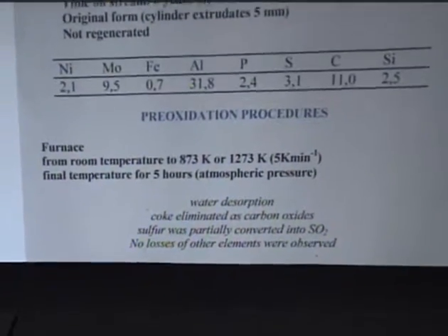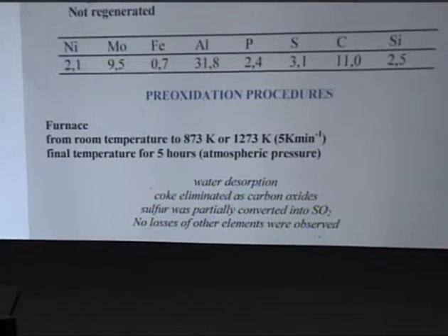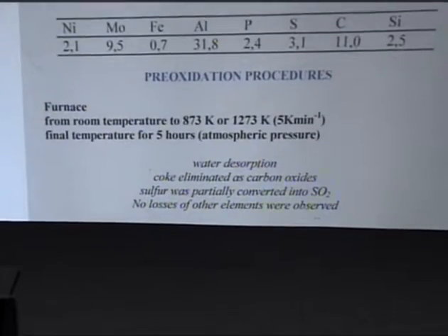The preoxidation procedure was very simple. We have used a laboratory furnace where the catalyst was placed, and the temperature was raised from room temperature up to 873 Kelvin or 1273 Kelvin at a rate of 5 Kelvin per minute. After which the temperature was kept for 5 hours, always at atmospheric pressure. During this procedure, we have observed the elimination of water by desorption, elimination of coke as carbon oxides. We have observed also some SO2 obtained by oxidation of sulfide species in the catalyst, because this catalyst, of course, was used in sulfide form during its lifetime, and no losses of other elements were observed.